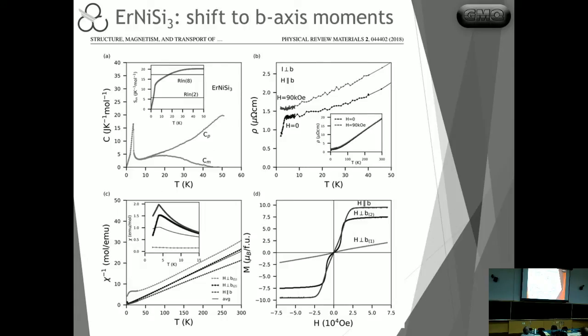So moving on into the erbium system, now we do see a shift from the A-axis into the B-axis. So here's the B-axis susceptibility, which is now higher, but we still have a strong component of magnetic response inside the plane. So you can see that this is a very gradual change, from completely A-axis in gadolinium, then things start happening in a mixture of directions. Here we start getting B-axis, but still with a mixture of directions. We see the same type of features as before, metamagnetic transitions, although no hysteresis is seen in this case.